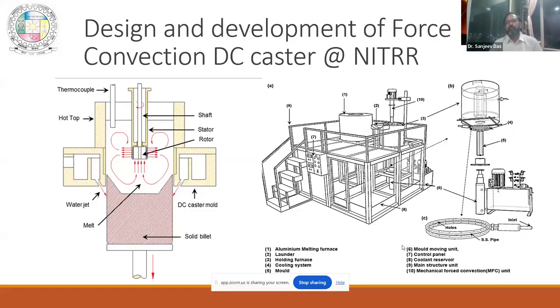Now what we have done with all this information I have shown you, we have made a DC caster. DC caster is a machine which is being used by aluminum industries, where there is a mold which is basically open at the top and bottom. You put the liquid metal there, you have a stopper plug. Initially the stopper plug is here, so you fill the liquid metal, and when the solidification starts, you draw down this stopper at the bottom, sliding it with the help of a pneumatic, electric or hydraulic system. And what happens, the liquid converts into solid directly. So a very small mold can cast a huge length of billets, ingots, like that.